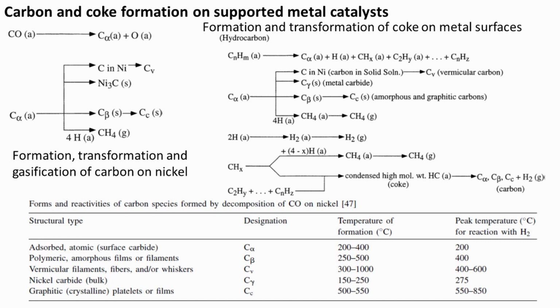If the rate of gasification is equal to or greater than that of formation, carbon or coke is not deposited. The rates of carbon and coke precursor formation and gasification both increase exponentially with temperature. Also, the difference between them varies a great deal with temperature because of differences in pre-exponential factors and activation energies. Thus, carbon and coke formation is avoided in the region of temperature in which precursor gasification rate exceeds deposition rate.